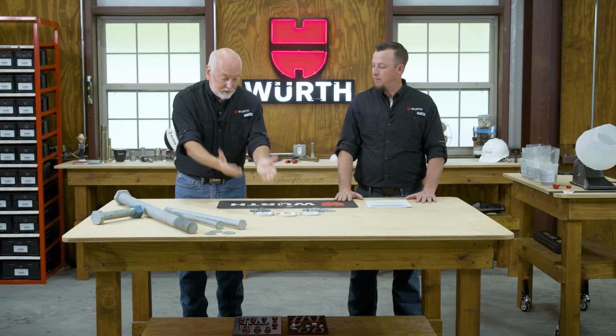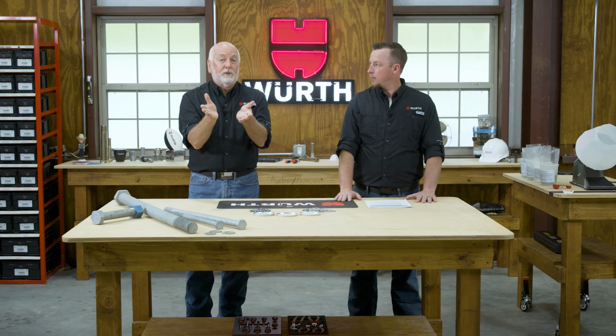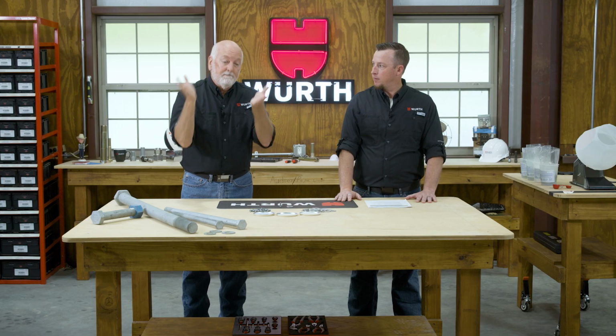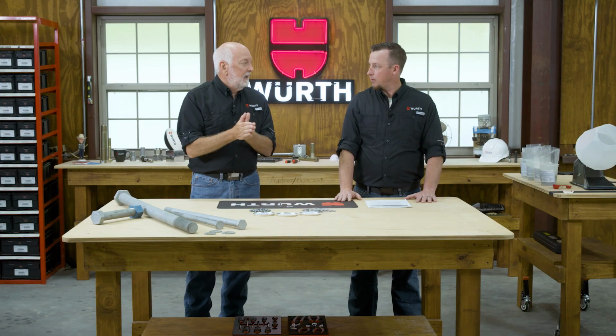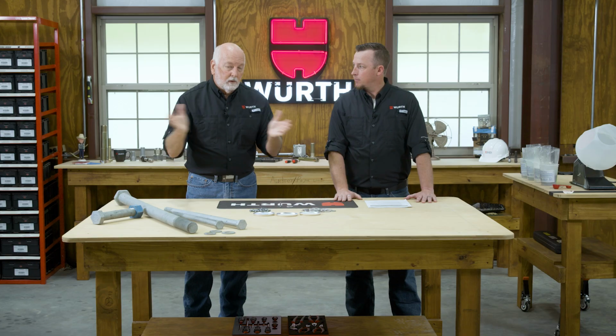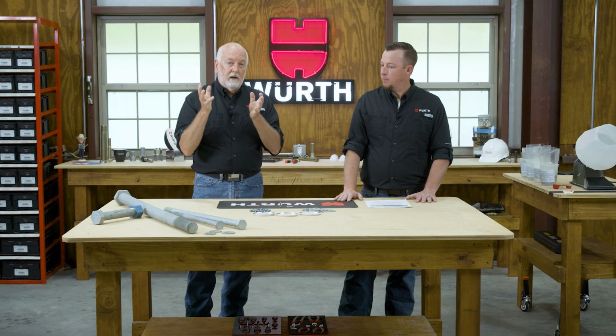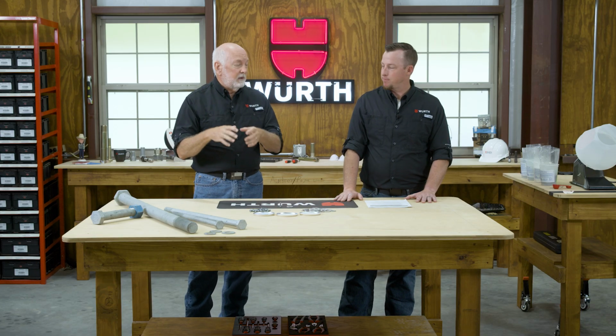My friends, this is a good coating to go to in high hardness parts. So our socket head cap screws right here, that are up at HRC 45, mechanical zinc. So we do a lot of high hardness spring steel this way up in the HRC 50s, no hydrogen embrittlement, and our structural washers that are F436 that are high hardness.